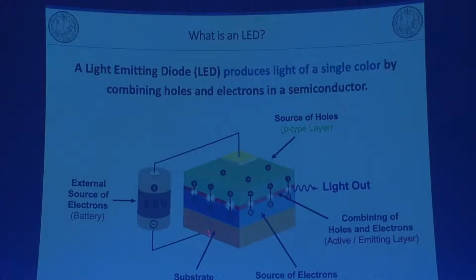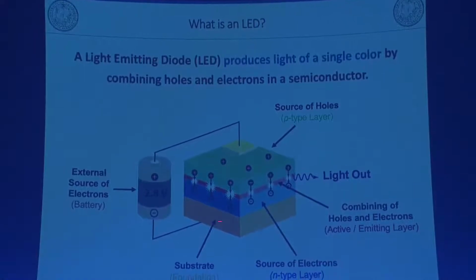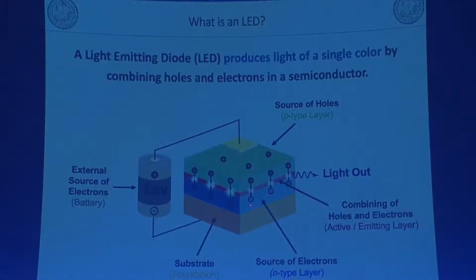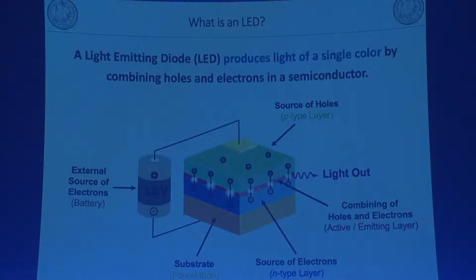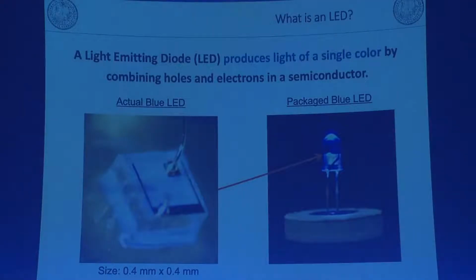So basically, the basic structure of LED and also laser diodes is very similar, just with a substrate. The substrate for LED is sapphire. On the sapphire substrate, we need 3 layers. One is the N-type layer, and the next is the active layer or emitting layer. And then finally, a P-type layer. We need just 3 layers to make an LED and laser diode. But in the case of blue LEDs, the missing layers were the emitting layer and the P-type layer. N-type layers had been available from the beginning. So we just had to develop 2 layers. After developing 2 layers, we could demonstrate the first high brightness blue LEDs in '92.